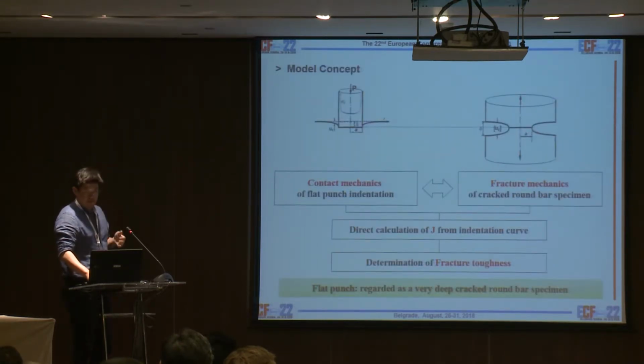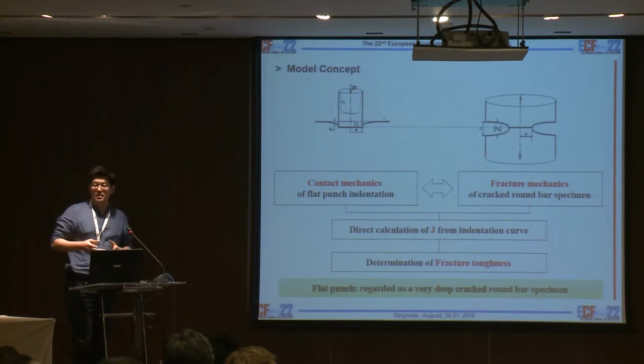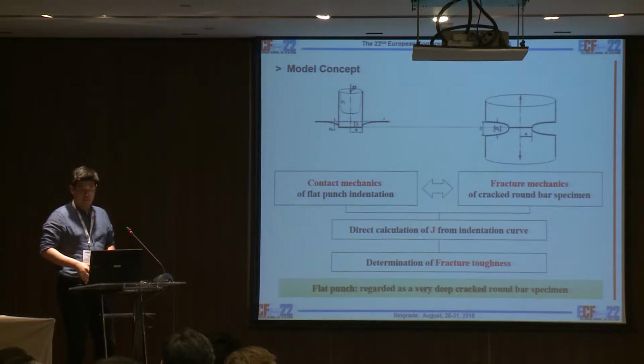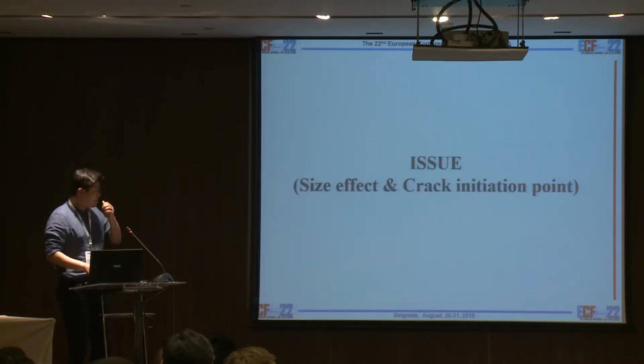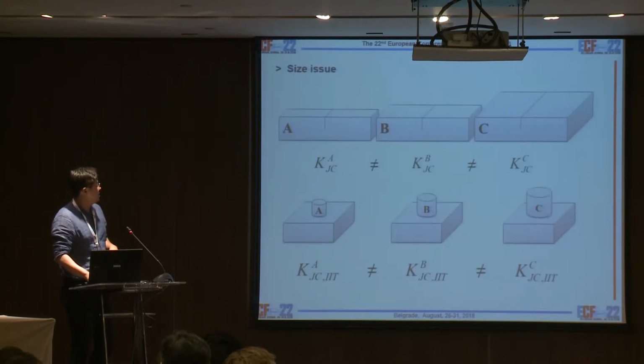So here is more of the concept. We assume that flat punch indentation can be thought of as a cracked round bar specimen fracture test. So from this flat punch load-depth curve, we can calculate the fracture toughness value. But still, we have two big obstacles in the indentation test. One is the size effect.